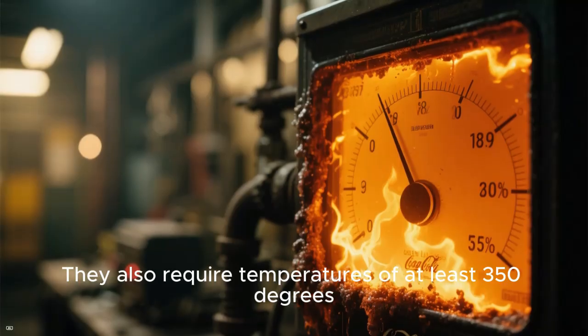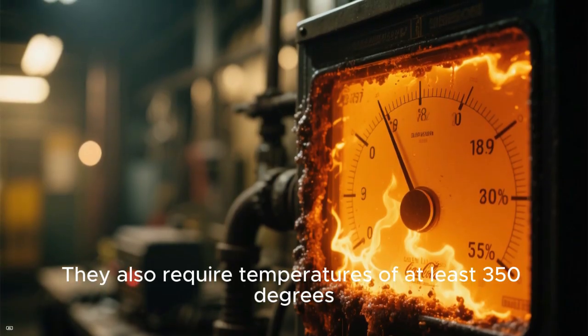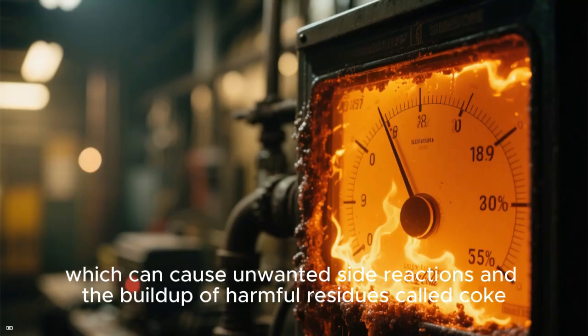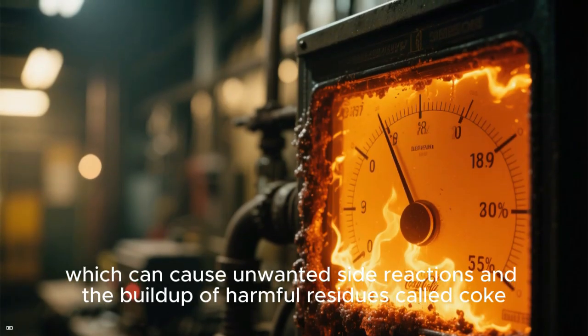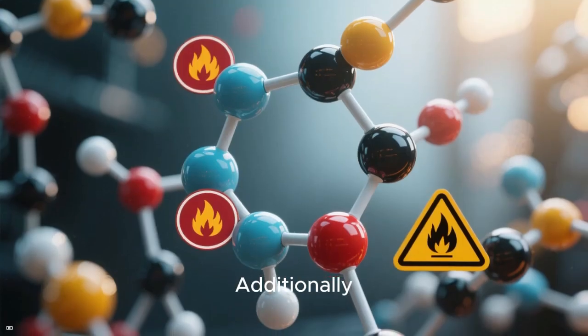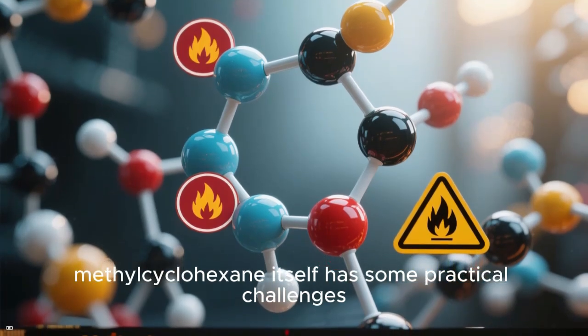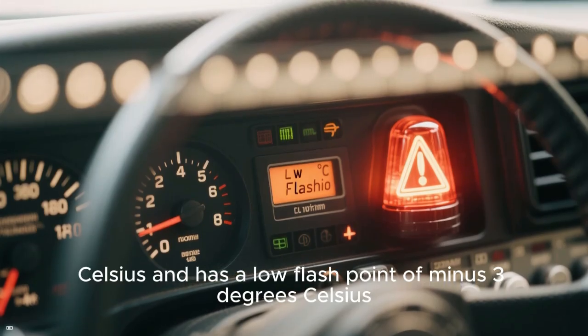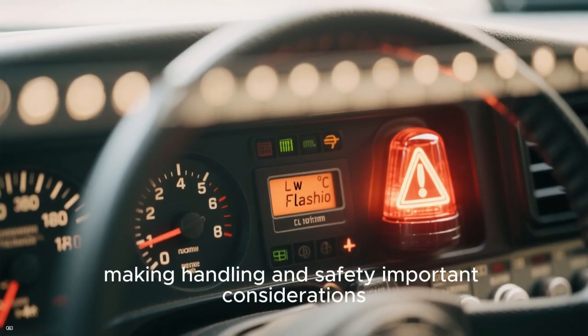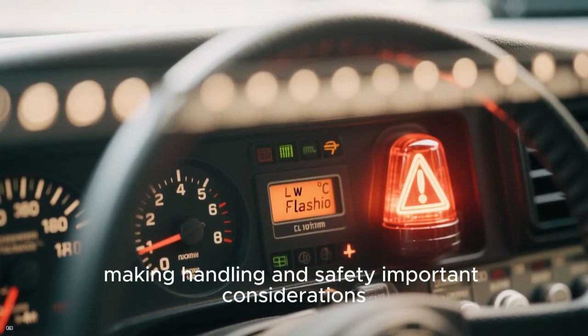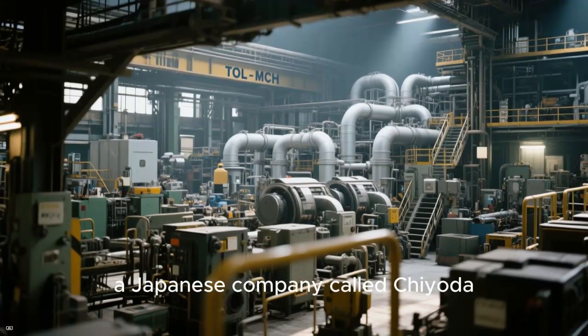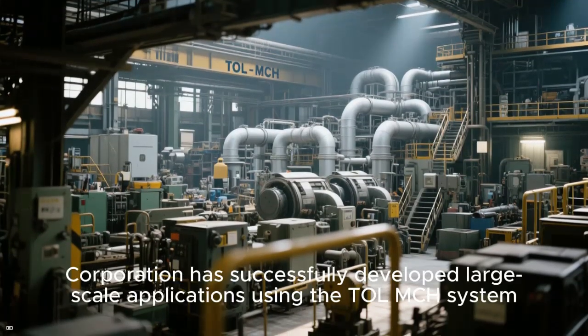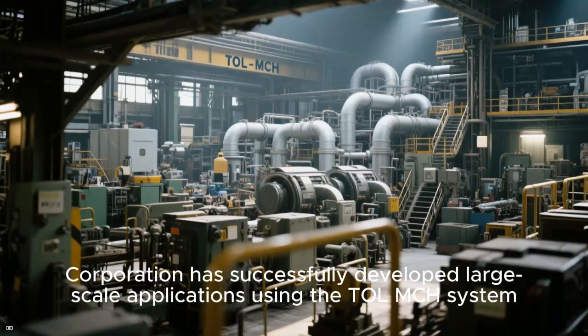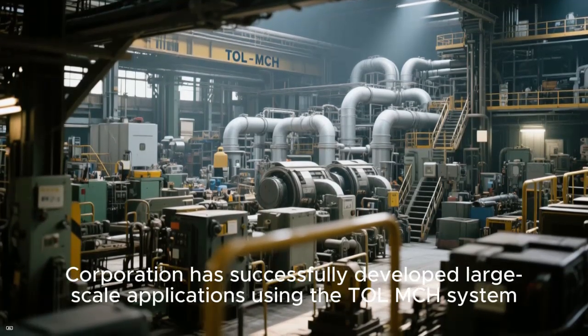They also require temperatures of at least 350 degrees Celsius to work properly, which can cause unwanted side reactions and the buildup of harmful residues called coke. Additionally, methyl cyclohexane itself has some practical challenges. It boils at about 101 degrees Celsius and has a low flash point of -3 degrees Celsius, which means it can evaporate or ignite easily, making handling and safety important considerations. Despite these difficulties, a Japanese company called Chiyoda Corporation has successfully developed large-scale applications using the TOL-MCH system, showing its potential for real-world use.